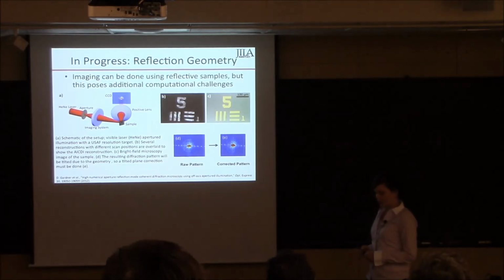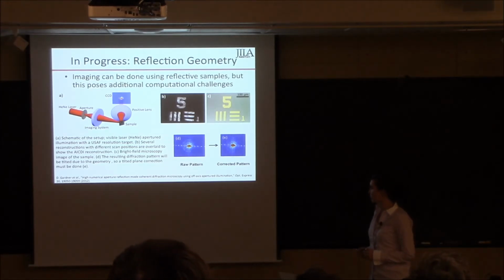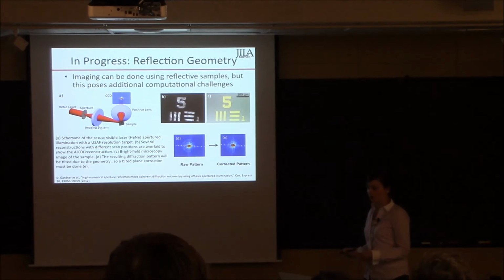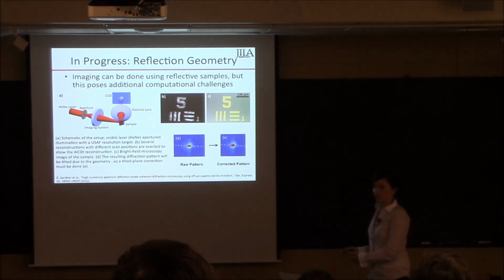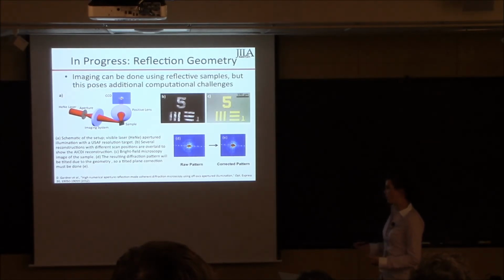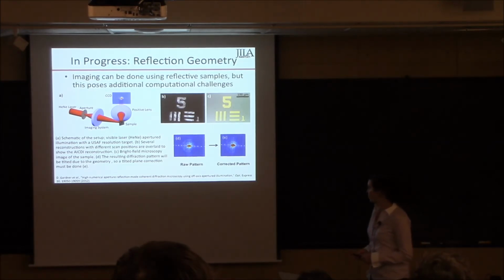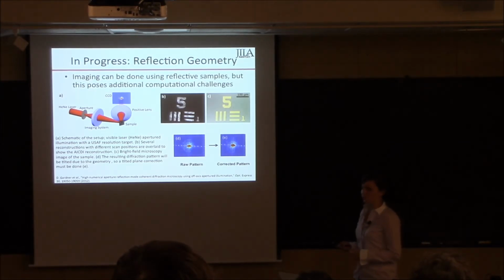So to correct this, we do what's called tilted plane correction, which is where we transform the diffraction pattern so that it looks like it was sampled on a linear grid. And this allows us to pass the diffraction pattern through the regular phase retrieval algorithm so that we can use Fourier transforms. So it's just a convenient way to be able to do the phase retrieval in the usual way.